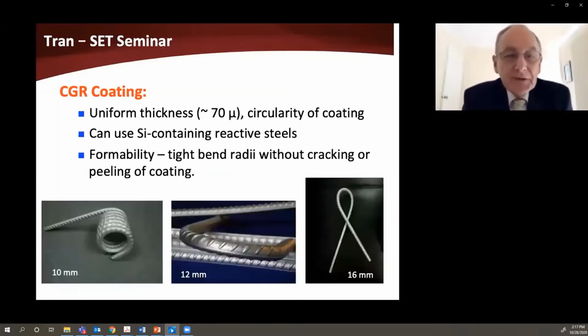The thing about the CGR coating, as it's called, continuous galvanized reinforcing, is that it gives you a uniform thickness up to about 70 microns. And one key thing about this is that you can use silicon-containing reactive steels. That is a bit of a problem with traditional galvanizing, because the high silicon level in reactive steels can cause the zinc coating to grow in an uncontrolled manner. So you need to be careful of that.